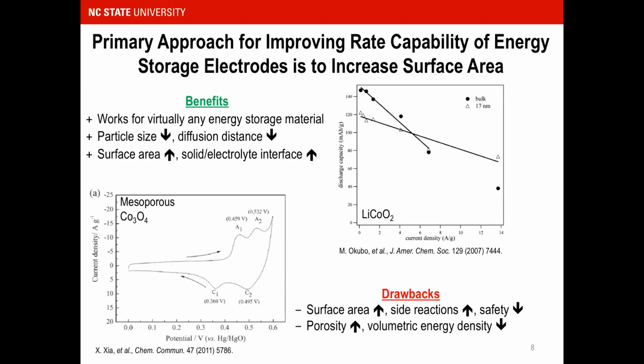But the drawback, and why you don't see materials like that in the industry, is that when you do this, you also increase the potential for side reactions with the electrolytes. These batteries operate not within a thermodynamic stability window of the electrolytes, so kinetically you're going to exacerbate that, and that's a safety problem. The other major issue is that you have almost too much porosity and your volumetric energy density goes down. So nanostructuring is not necessarily the best way to go for intercalation type materials.